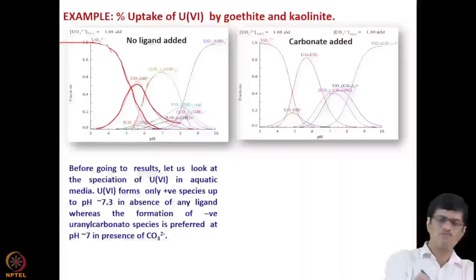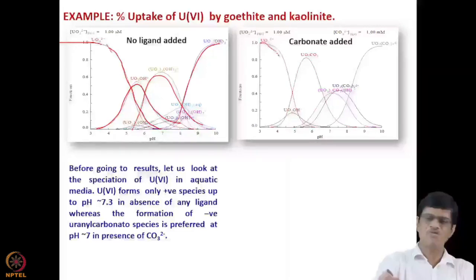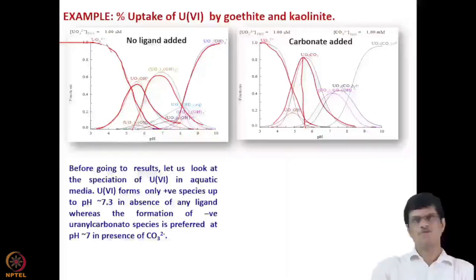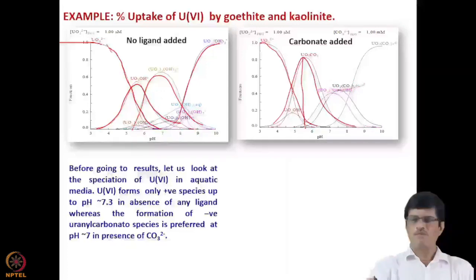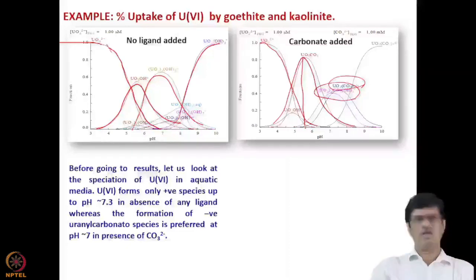This is how the uranium ion speciation evolves with increasing pH values. If carbonate is present in the aquatic system, carbonate complexes are formed. At low pH, the uranium ion species are as before, but around pH 5.5 uranyl carbonate species form. At higher carbonate concentration or higher pH, uranyl carbonate species with more carbonate ligands are formed, or polymeric dimeric species containing both hydroxyl and carbonate complexes with two uranium moieties.